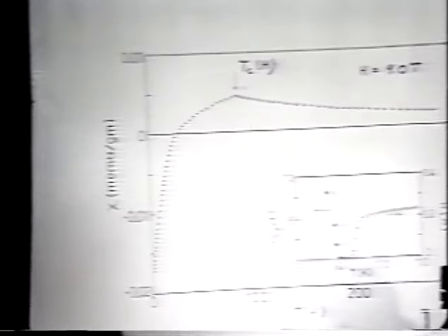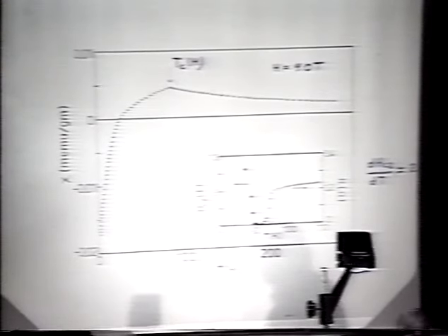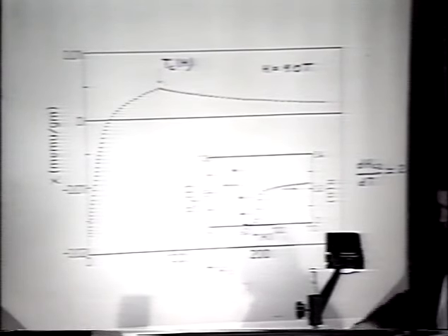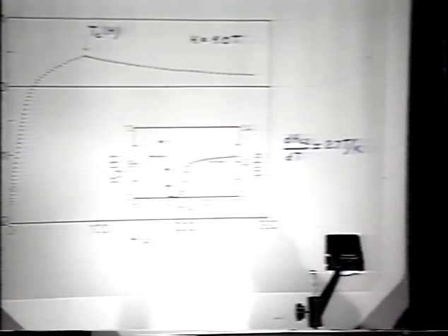If you look at warming the sample in field, the magnetization goes away. If you blow this region up, there's a paramagnetic component to it, which I think has also been mentioned. It is shown much stronger here in this higher field. This we take as the critical temperature in field. It's sharp, fairly distinct. It certainly sets an upper limit on the critical field. And if you then plot that, it gives you this linear dependence near TC and a dHc2/dT of about 2.7 tesla per degree.